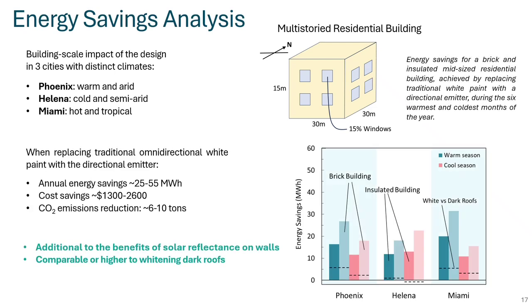Then, for a residential building, when you replace a traditional white paint with this directional emitter, we found energy savings up to 55 MWh annually, which corresponds to cost savings up to $2.6 thousand a year and up to 10 tons of CO2 emission reductions. These values are significantly higher than the benefits you would get by painting a dark roof in white, for example.